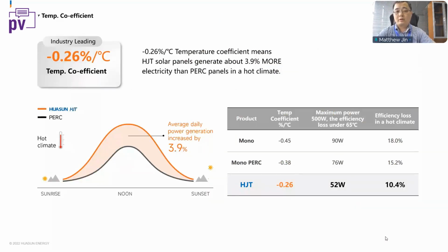For the temperature coefficient, minus 0.26% per degree Celsius. So for example, for a 500 watt panel, if the environment temperature reaches 65 degrees, comparing mono PERC and HJT, the efficiency loss in hot climate goes from 18% to 15% and to 10%. By this performance, the HJT can get average daily power generation increased by around 4%.